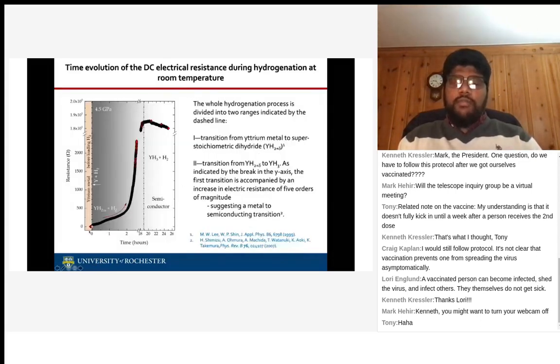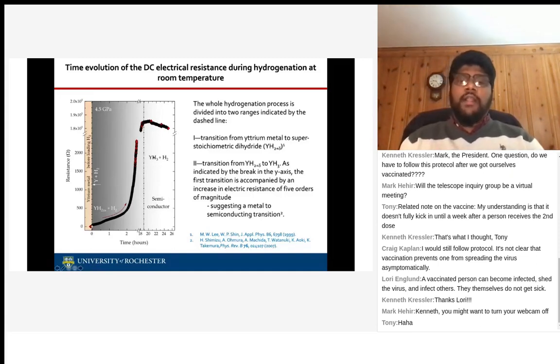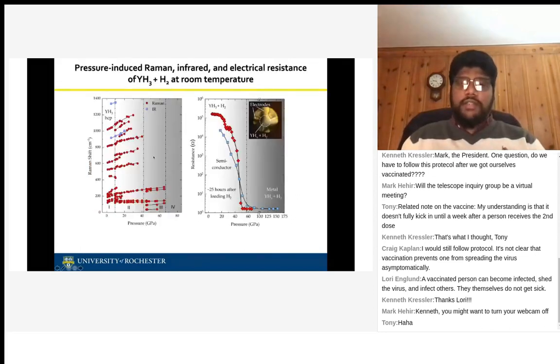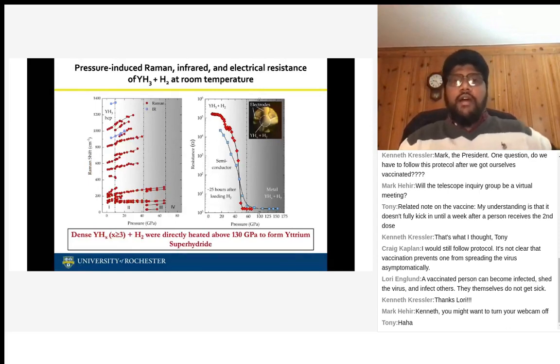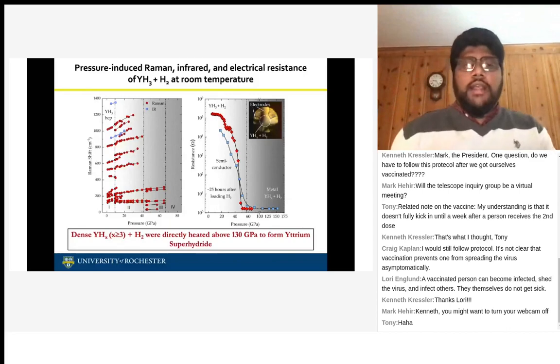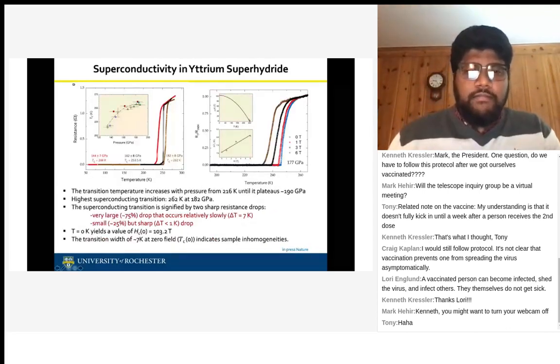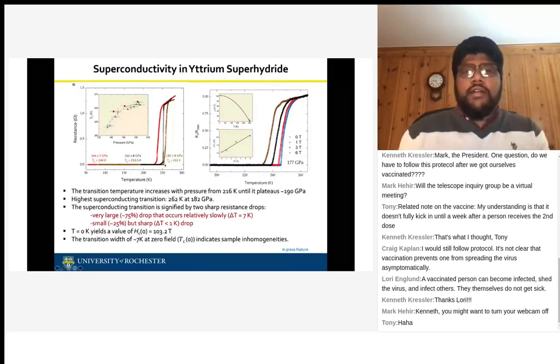This is the electrical resistance in pure yttrium. As soon as hydrogen starts to come in, it reacts and becomes yttrium hydride, and you see that the electrical resistance goes up and it becomes a totally different material, YH3 plus H2. When you squeeze this material to higher pressures, that's where we start to see the high pressure superconducting properties of this material. This is the higher pressure form. And if we look at this graph, this is the temperature and this is the electrical resistance. If you cool it down, you see the electrical resistance drop and then vanish around 262 Kelvin. So you made a new material with superconducting properties as high as 262 Kelvin.